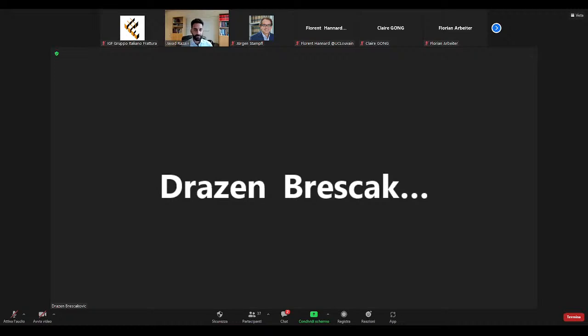Thank you for your question. Yeah, we already did this. That will be presented in some future works. The advantage of this work is that we can calculate the crack path, for example, for 1,000 paths in several minutes on a normal workstation. So it is very easily adaptable to a range of multiple arrays of holes, to find the right geometry in a composite material to arrest as many cracks as possible. It's because the method we used is an interpolation procedure. And in our case we used a superposition procedure to adopt as many holes as we want, to see if we get the most toughness of the material and as much stiffness as possible.